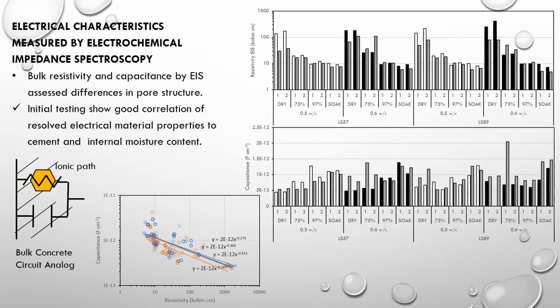But interestingly enough, when we plot them together, if you see in this graph here, we'll correlate the capacitance of the concrete to resistivity of the concrete materials. We start seeing separation of the data between the different water cement ratios and rock type. So the blue colors represent the 0.6 water cement ratio, and the orange represents the 0.5 water cement ratio. Solid lines represent the 57 rock, and the dashed line represents the 89 rock. And so we see separation of materials.